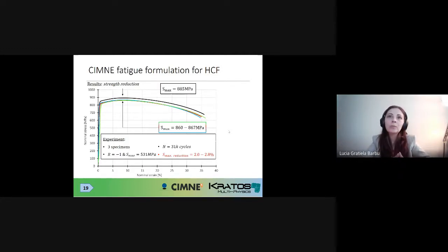And what we wanted to see is if you apply a determined number of cycles, which we decided together is going to be 31,000 cycles, and then you break the sample monotonically, we were interested in finding out if the maximum level of stress attained by that specific specimen after having applied 31,000 cycles was the same as in the beginning, the same as for the virgin material or not. What they saw experimentally was that there was a reduction in the maximum stress achieved inside the specimen of about 2.8%. Basically, the maximum level of stress went down from 885 megapascals to about 865, as an average.